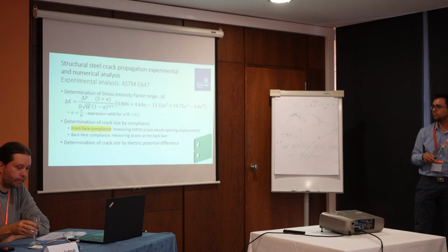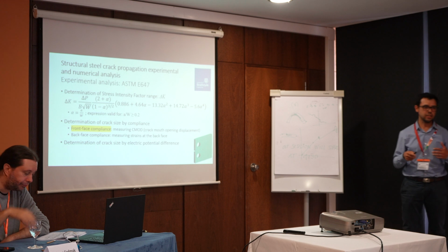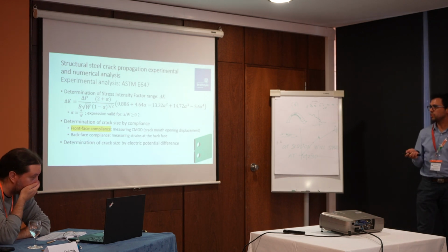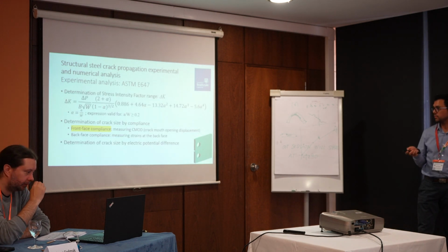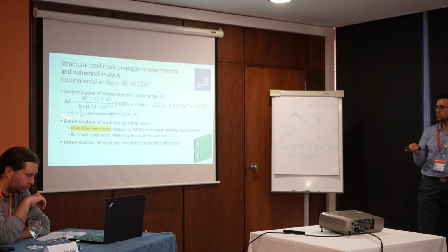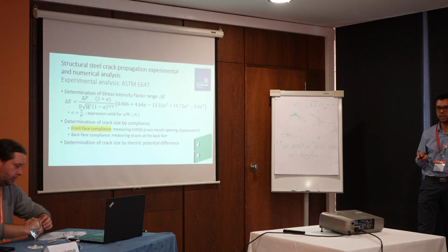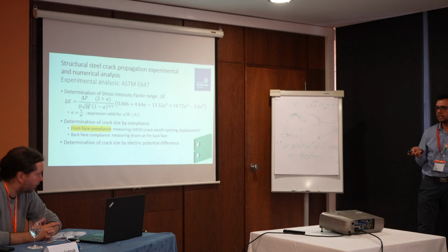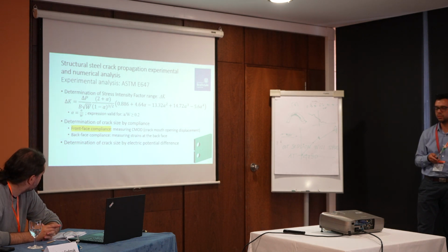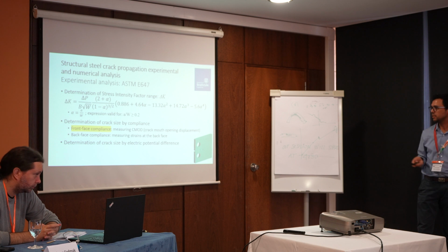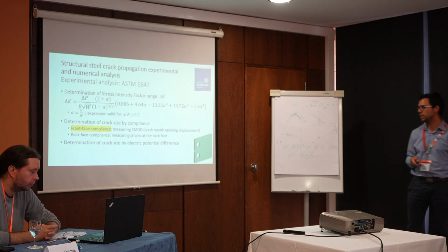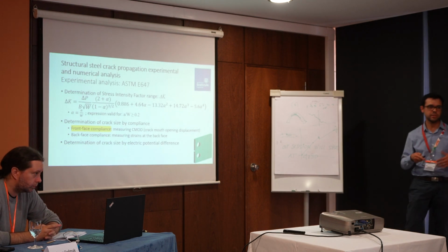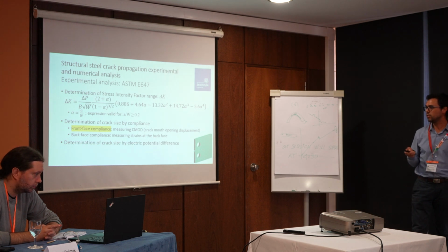Well, the ASTM E647 gives you this expression in order to calculate the stress intensity factor, right? According to the compliance of the test. And for this analysis, we use the front face compliance, where we measure the CMOD, the crack mouth opening displacement, in order then to determine the Paris law coefficients.